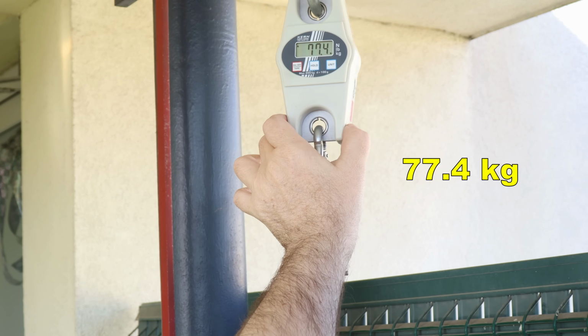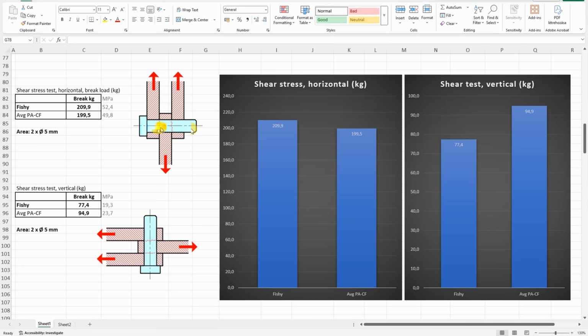Shear test, vertically printed. It had double break. Printed in horizontal position, fibers always helps. And this filament was a little bit stronger compared to the average PA-CF, a little bit above maximum for my hanging scale. I didn't have to switch to the crane scale. Printed in vertical position, a little bit weaker compared to the average PA-CF.